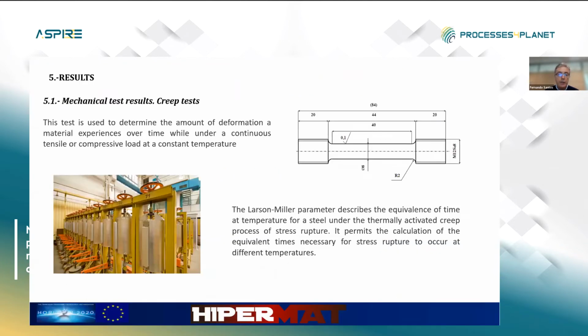The main critical aspects we have considered are creep and crack growth rate. So we have gone over creep tests. This is the type of test bars that we have prepared. These are the type of machines that we have used. And we have compared the results using the Larson-Miller parameter, that is the equivalence of time and temperature for a steel under a thermally activated creep process of stress rupture, and it permits the calculation of the equivalent times necessary for a stress rupture to occur at different temperatures.